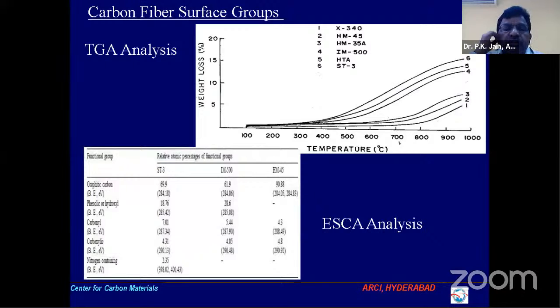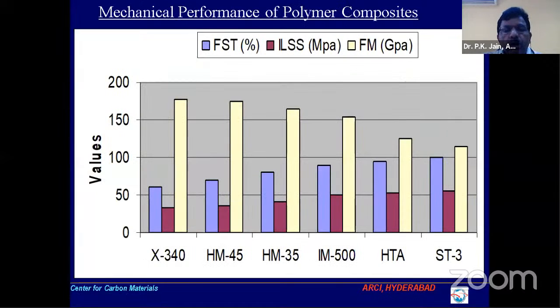To know the surface energetics of surface groups, we did the TG analysis and found that number 6, which is the high strength fiber, has the highest surface groups, and number 1, the neutral one, has the lowest surface groups. Accordingly, as the modulus increases, the surface groups also become very few. And from the ESCA or elemental analysis, we estimated the amount and type of surface groups, and then tried to develop the composite out of it.